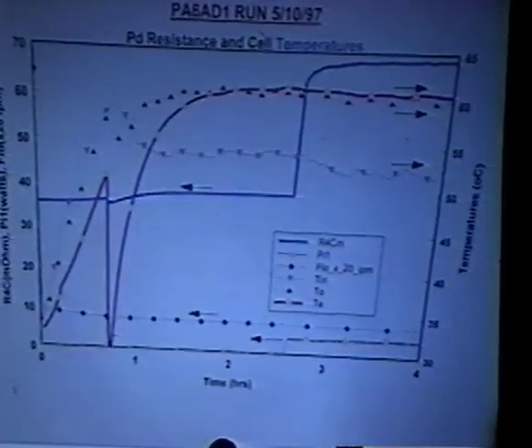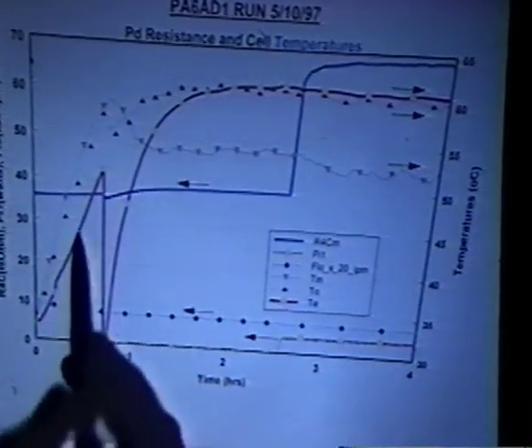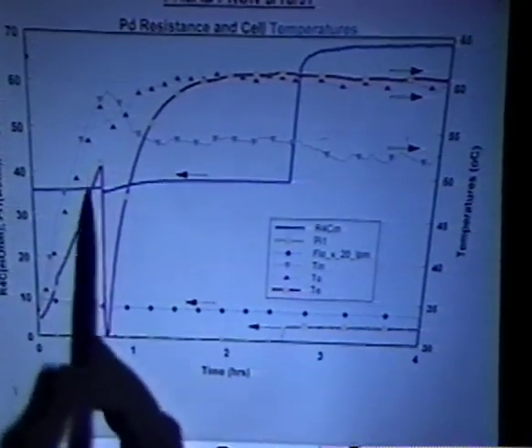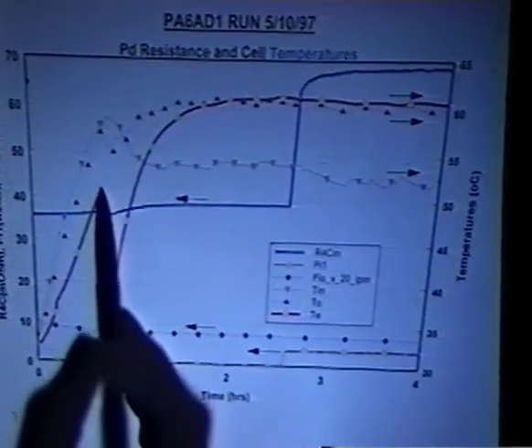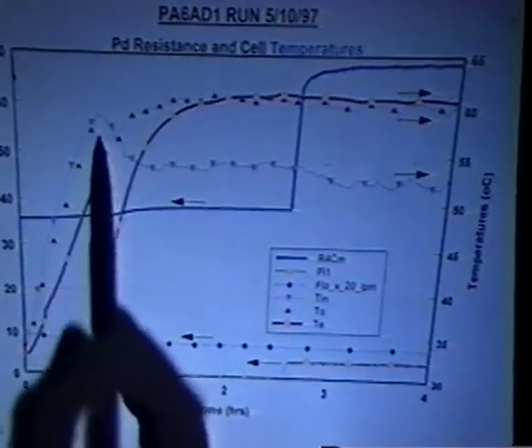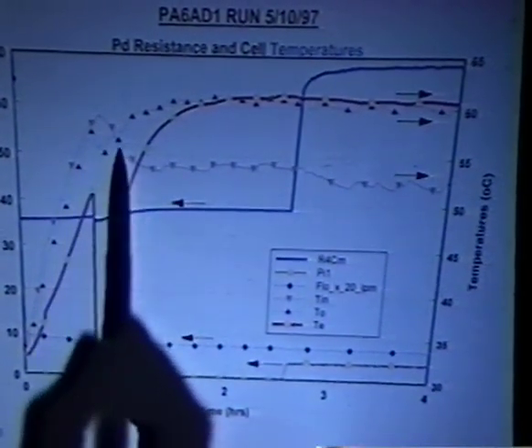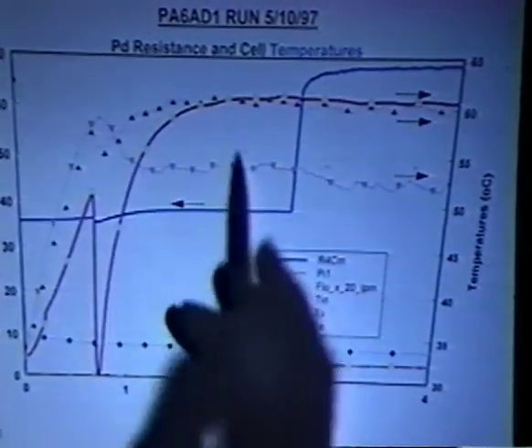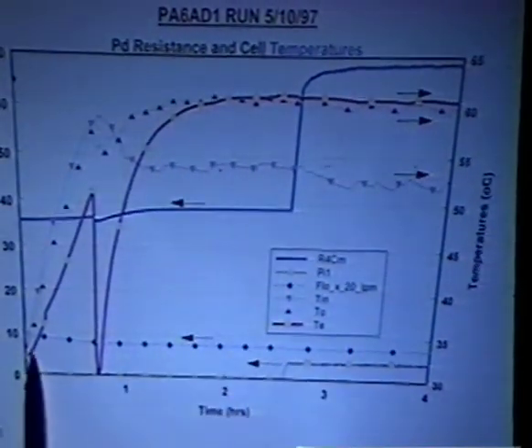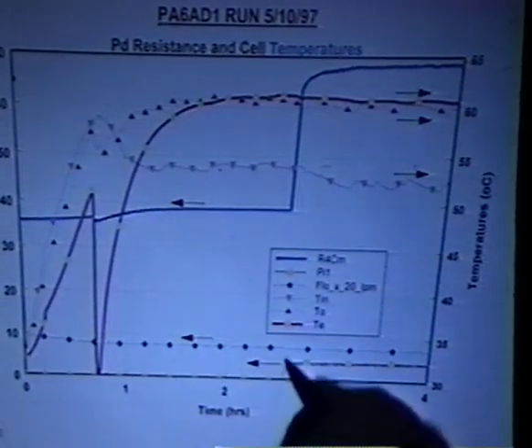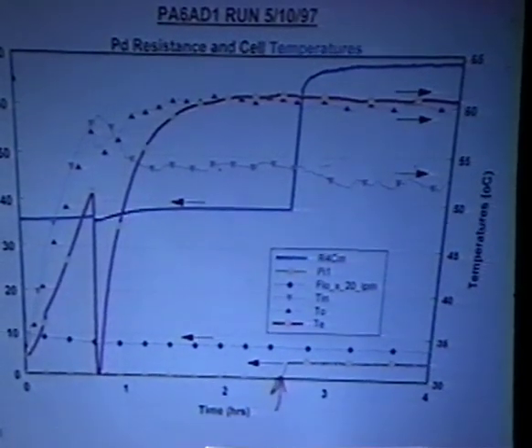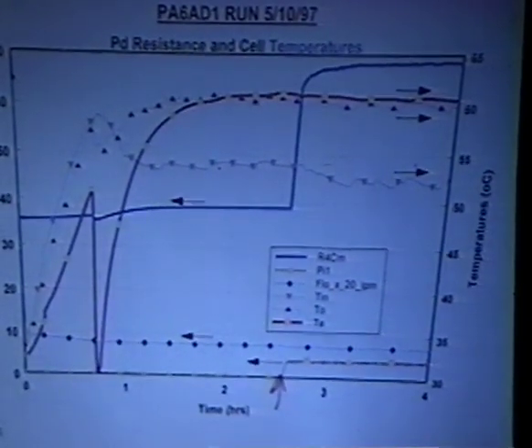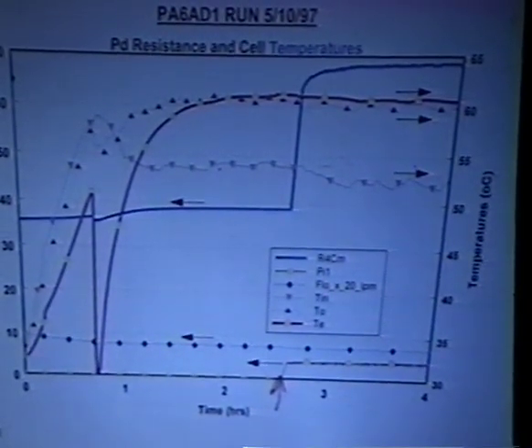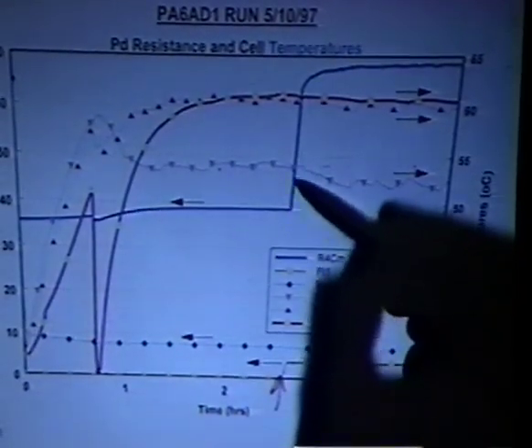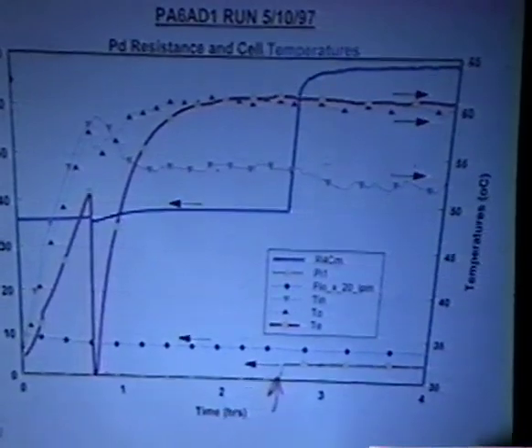Let me show you just a real quick blow up here of the beginning of this run. Right in here, this is the cell temperature with no solution poured in. So it's empty. We're seeing the cell temperature come up. As soon as the cold solution was added, right in here, you start to see this separation between the inlet and outlet. And there's a little changeover, and then this large delta T that appeared. And again, this was all during no current. The current is turned on at this point, electrolysis current. So this power actually shows up before this palladium was ever charged. And of course, once we turn the current on, you see the resistance of the film going up and peak.